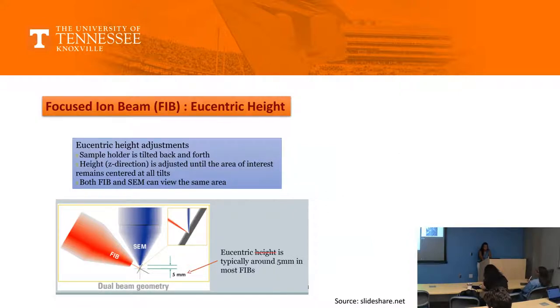Now, the first thing that is important here is eucentric height adjustment. So you see here, you have the FIB gun, you have the SEM. So you are looking through one gun on your sample, but you're aligning it with respect to another gun and want to operate the entire operation through another gun, right? So here is your sample and your material. You are trying to use the FIB gun. So eucentric height is extremely important, and it is typically around 5 millimeter in most FIB. So the distance that you see is 5 millimeter.